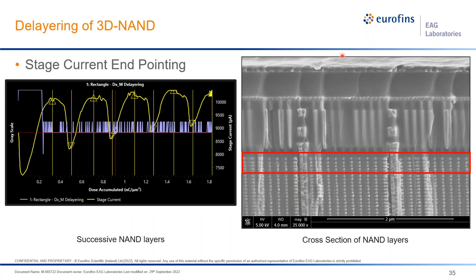So here on the right, we can see a cross-section of the NAND structure. So we would use the ion mill to remove all these upper layers here and get us down to this region where we're a little bit closer. And then we can start doing the DX-assisted delayering. We can then use stage current endpointing to very precisely understand where we are in the structure. And here in this case, you can see we go through four repeats of the NAND structure and stop here in the fifth. And so that's essentially going through each of these layers here on the right.